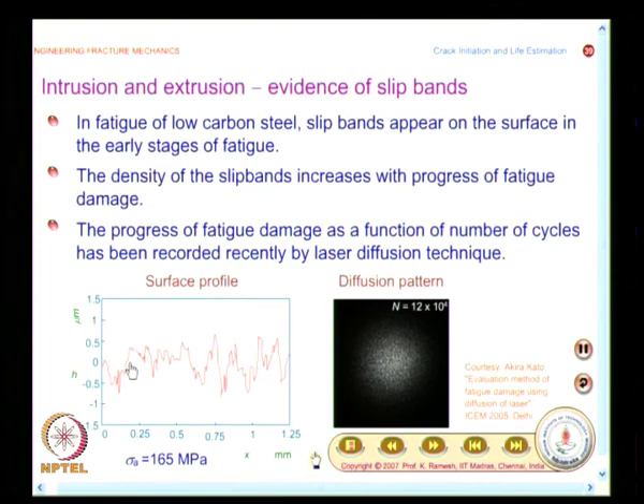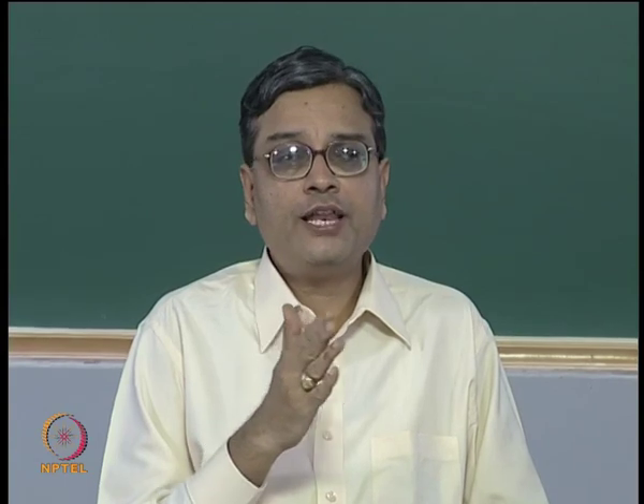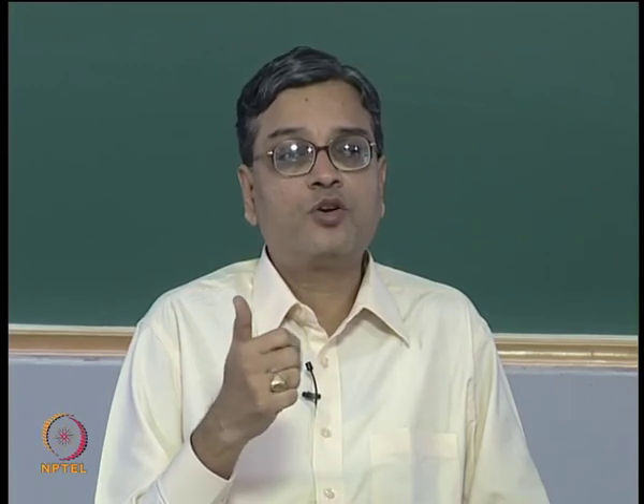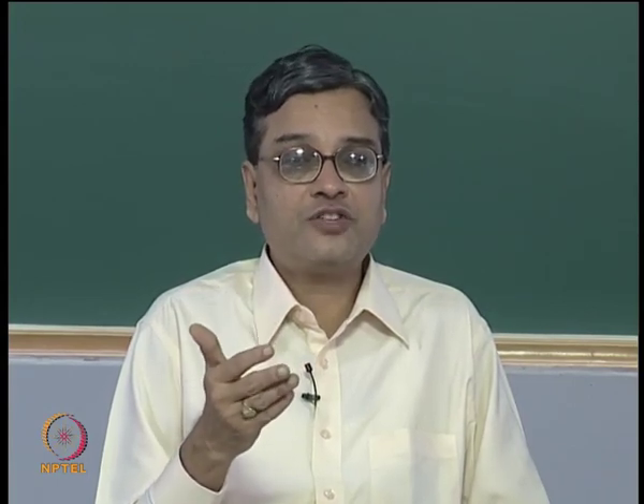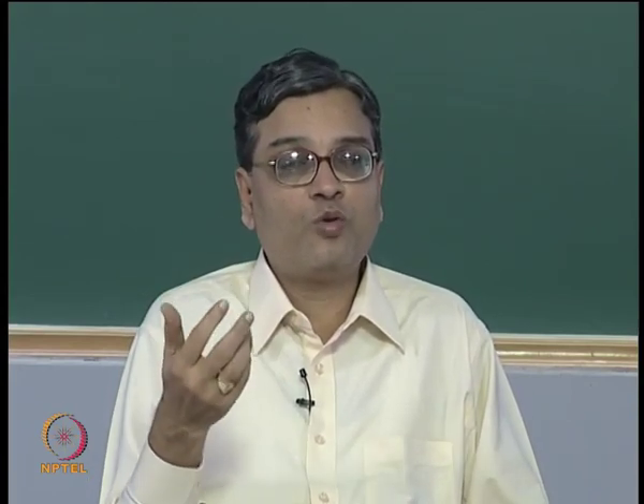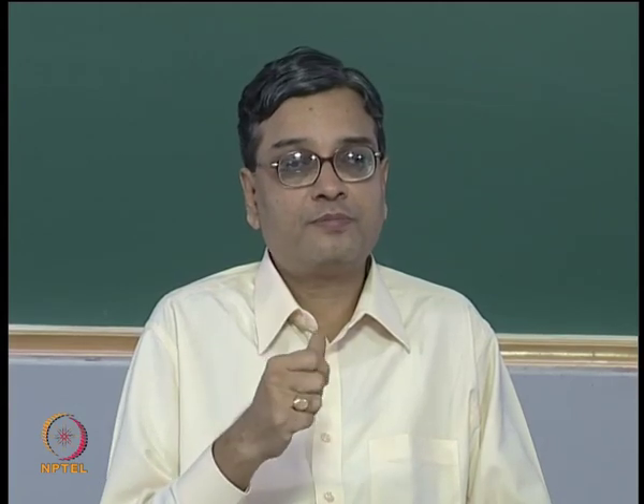So, in this class what we had done was, we had looked at Wheeler's model to explain the overload phenomena, and we have looked at how retardation can be calculated. Then I said for any meaningful calculation of life, you will have to depend on computer software, because even estimation of stress intensity factor as the crack grows, you will have to bring in geometry factor, only then the calculation is accurate. Then you have to bring in crack closure effects, then you have to bring in overload effects as well as the environment. So, it is better that you go and look for software that is available, one is NASGRO, published by NASA, there is another one done by US Air Force which is called AFGROW.